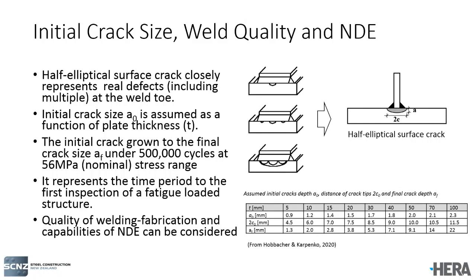So the reason for this crack is we don't want any crack, but a crack is a real possibility in any welded structure. And we have to assume that the crack gets undetected by NDT, right? The size of the undetected crack is on your right corner. The size of that crack is a function of the plate thickness. And if we do a cross comparison between the size of the crack, the so-called initial crack A0, we need to make sure it is actually detectable using NDTs. We can include a larger crack if we need to, but these are crack sizes we are confident can be detected.